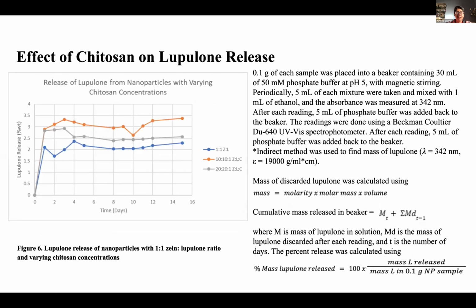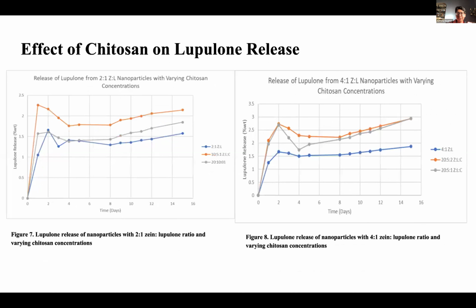This brings us to the effect of chitosan on lupulone release. Another thing we were expecting to see was that adding chitosan to our nanoparticles would hopefully increase the release of lupulone from our nanoparticles because of their differing electrostatic attractions. In the first graph, you can see that the line in orange is the one that included chitosan, and the gray one too. The blue one didn't have chitosan, and you can see that the release is greater in those that did contain chitosan. Here you'll see the same thing. These were just different concentrations, different ratios of the 3 components.